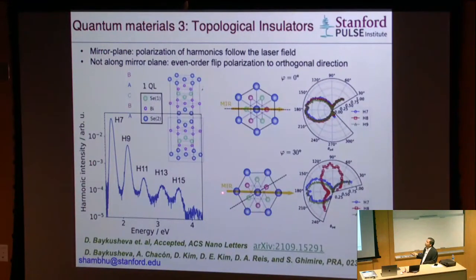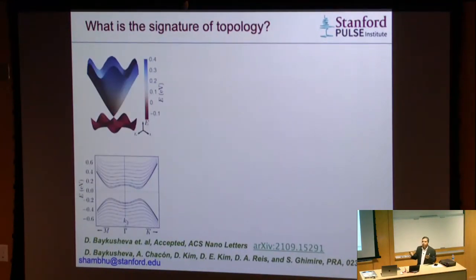When the laser is polarized in the direction of the mirror plane, everything is polarized in the same direction. When the laser field is polarized not along the mirror plane but somewhere else, like at 30 degrees, we produce these even orders. They flip the polarization and they become orthogonal. This is very similar to MoS2, and yet it may not have anything to do with the topology. It's just the inversion symmetry broken system, which is the surface, right? Now we're interested to find out really what is the signature of the topology. I'll tell you a brief version of that.